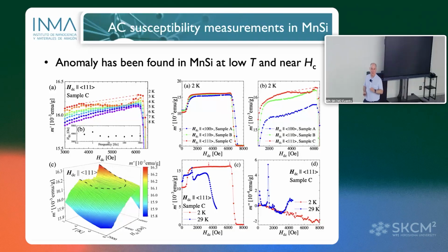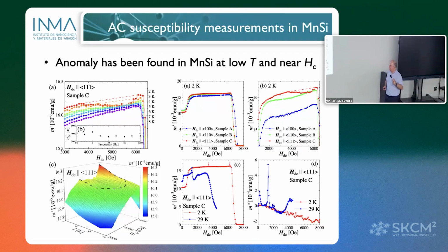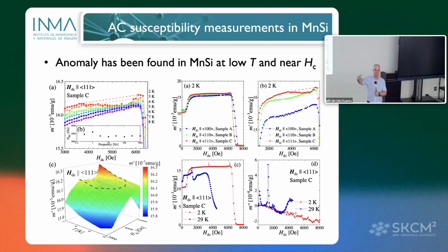Okay, we know that the skyrmions are not stable there, but there are two important points. Our model was a very simple model, for only one spin, in the continuum limit and with cubic propagations. Manganese silicide is much more complex. And in our model, we didn't include anisotropies. Maybe anisotropy should be included as a perturbation, because the experiments for this phase tell you that anisotropy exists, since we observe it in one direction but not in the others. Then the model needs to be updated. We know it's not correct to describe this. Maybe anisotropy must be included later.